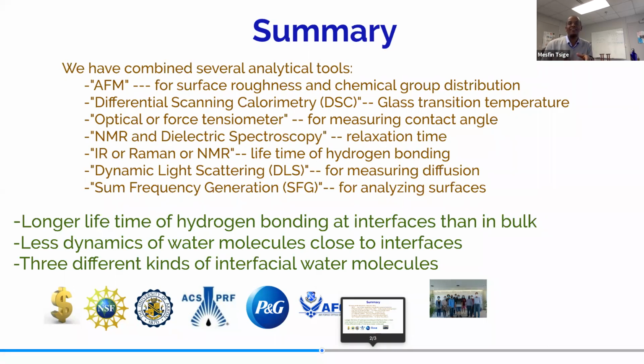I have to mention that there are so many water models. It could be more than 50 or 60 water models that actually exist. Water turned out to be a very difficult molecule to simulate. The polymers are much easier than water actually, because of its anomalous properties. When you bring them in bulk versus at interface, depending on what model is used, you may find different properties. But the models that we have used are called TIP4P and SPC/E. The two water models have been proven to work very well, both in terms of bulk and interfacial properties of water. So the answer to your question is yes, DFT, ab initio kind of calculation would be very helpful to capture those hydrogen bondings. But given that it is dominantly electrostatic, it can be captured through classical simulation like molecular dynamics. Okay, thank you.